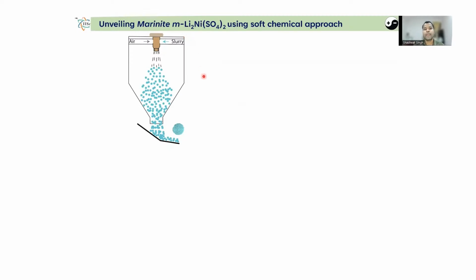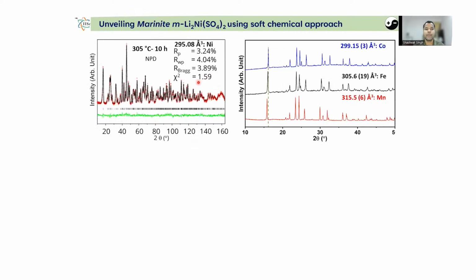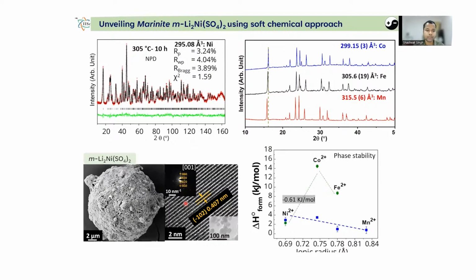So, to synthesize that metastable monoclinic phase of the nickel analog, there was a need to use some soft chemical approach, and therefore we went towards spray-drying synthesis routes, and with the help of this route, we have synthesized this compound at a low temperature of 305 degrees Celsius for 10 hours. As you can see, the phase purity is very high. And moving ahead, we then extended this route to other members of these compounds.